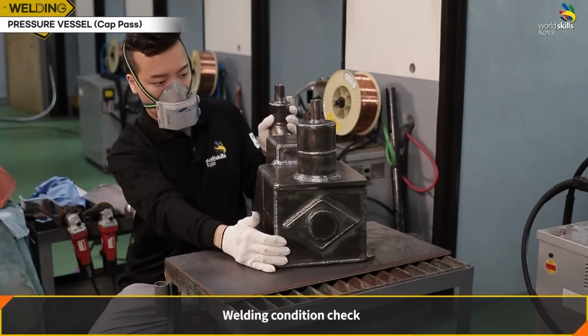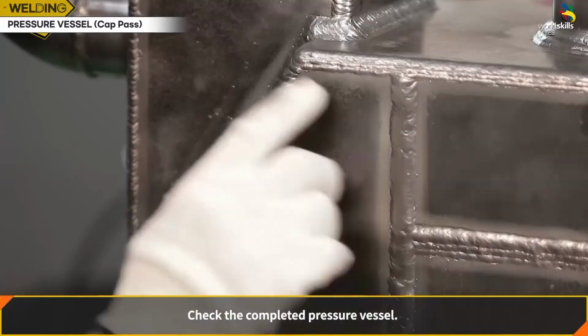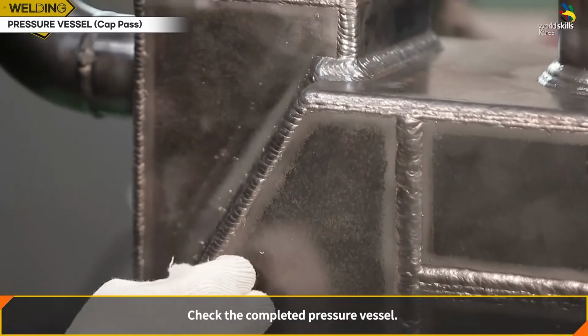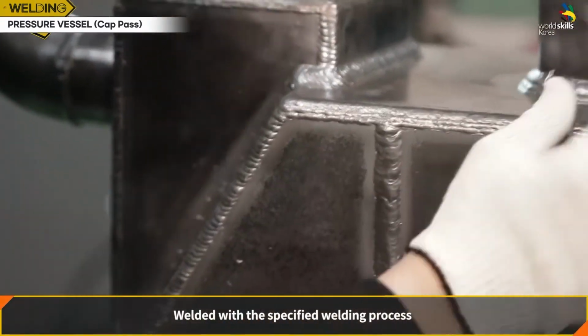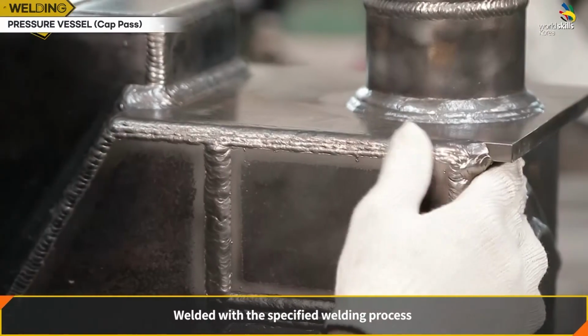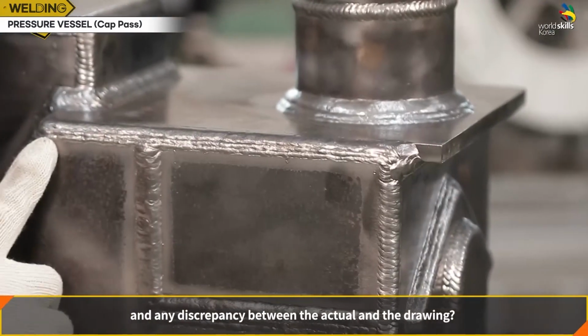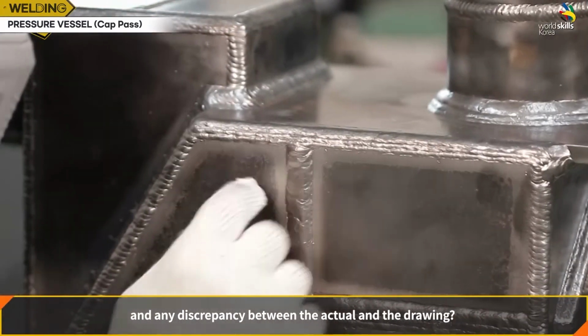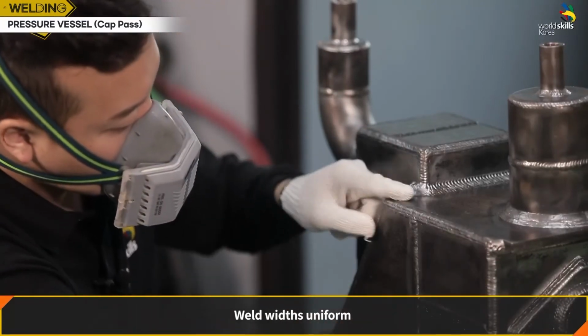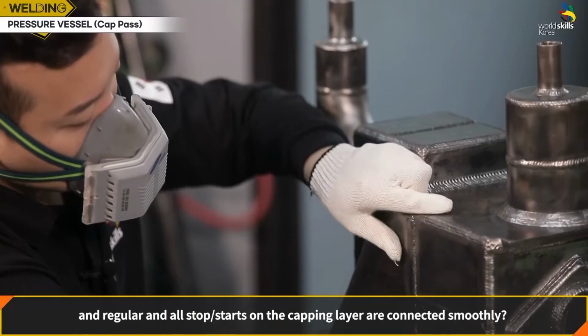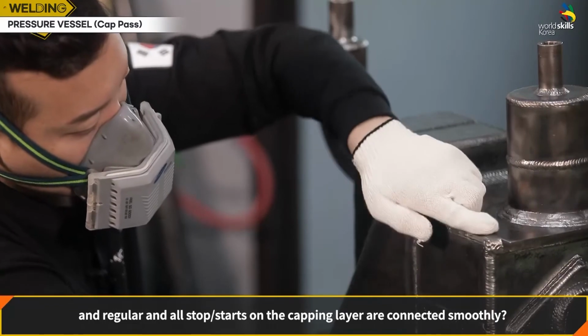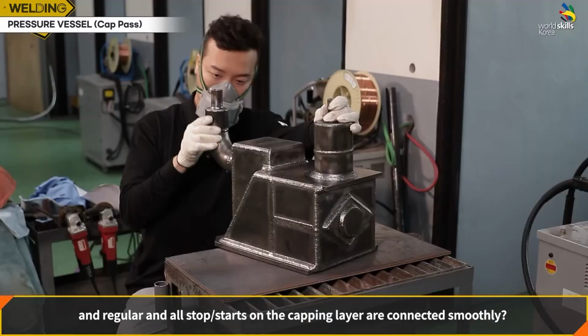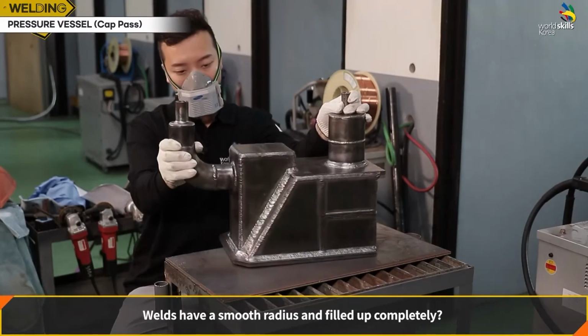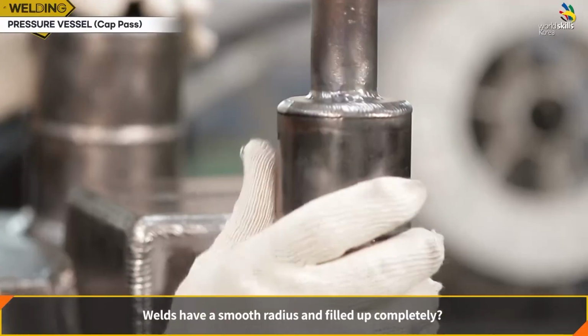Welding condition check. Check the completed pressure vessel. Check if it is welded with the specified welding process and for any discrepancy between the actual and the drawing. Check if the weld widths are uniform and regular and all stop-starts on the capping layer are connected smoothly. Check if the weld has a smooth radius and is filled up completely.